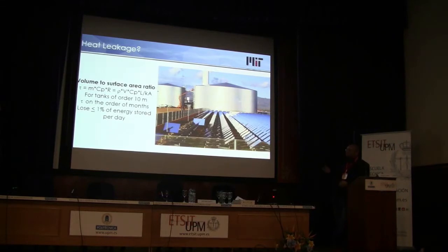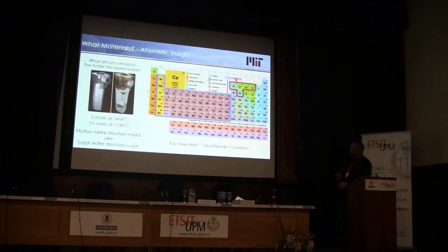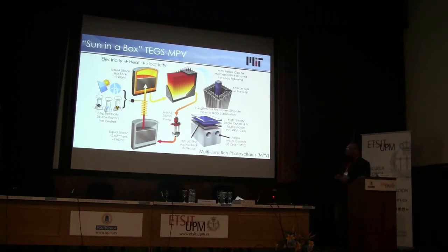So the main message from this slide is really that for our system, we're interested in making it large. As you'll see, we have the ability in this system to tune the power to energy stored ratio, or the number of hours of storage. We can tune that pretty far. But what is key is that at the commercial scale, we do need it to be big. We can't really get around that. Again, we're going with some kind of ceramic as opposed to metal-based containment because we're going to extremely high temperature. And so this is the system overview.